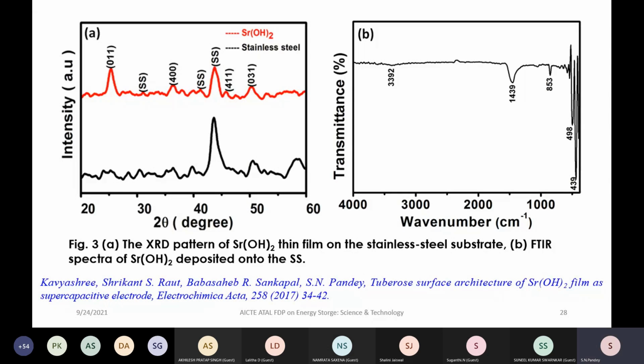So at 439, one can see here that one peak that we are getting is due to the strontium-oxygen bond, and this 4981, no, sorry, 98 inverse, it is giving the hydrogen strontium OH, HSrOH. In addition to that, we are having the 1439, that is the vibration of the water molecule, HOH. And the peak located in the range of 3300 to 3800 is the stretching vibration of the physically absorbed OH, because we are doing this in atmosphere, so that OH has been absorbed there.